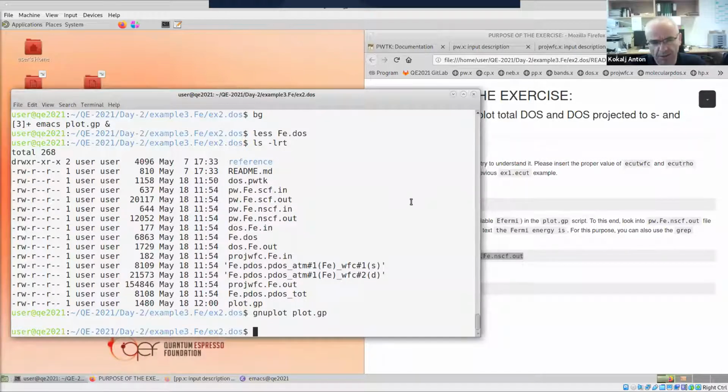This will affect the K-point convergence. So as far as the cutoff is concerned, it really does not depend on the structure because it's more of an atomic property. The cutoff for the wave function depends on which pseudopotentials you take. For iron, we took an ultrasoft pseudopotential. If we would take a norm-conserving one, the cutoff would be much higher. And this cutoff is atomic, so it depends on the pseudopotential, and the lattice parameter doesn't really have a role here.